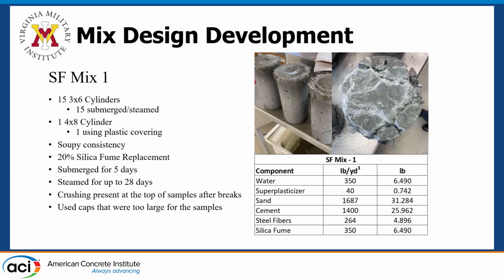So going back to those caps that I was talking about earlier, made for the 4x8 cylinders, we attempted to break them using that because there wasn't a smooth surface. We figured we wouldn't get proper breakage. However, we found that there was a large amount of crushing, and that's a problem we fixed later on. But we figured the strength could be a lot higher. As you guys can see, there was frictional confining stress on both ends, and that's what kind of caused breakage in one end and no break throughout the cylinder.